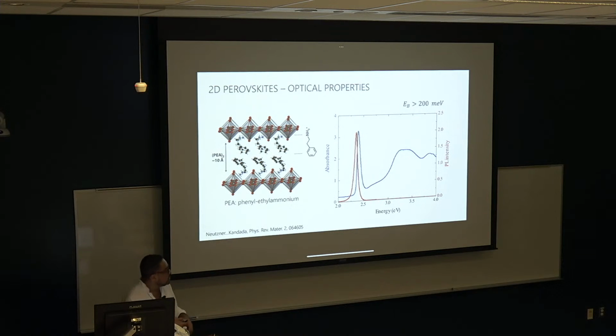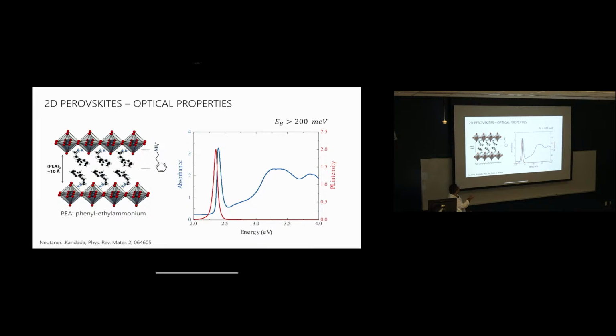So here what we have is the absorption spectrum, and this is at room temperature of this very material. And this would be a relatively thick polycrystalline sample. I don't know, 100 nanometers or so. For us, that's thick. And you have features here. This is just the continuum absorption, the band-to-band absorption. But down from the band edge, you've got this, what appears to be at room temperature, very well-defined resonance, and that's your exciton. That's the optical signature of excitons. What are excitons?